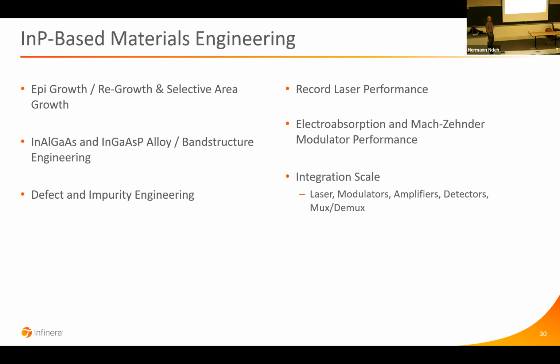We started Infinera in 2001, and some of the things that we did were beyond what is known in the literature: new techniques around growth and regrowth, as well as selective area growth. Also, there are things that people don't appreciate about the band structure, believe it or not, even on a mature technology like indium aluminum gallium arsenide. And probably most importantly, a lot about defect and impurity engineering. With this, we were able to have record laser performance, the narrowest line width indium phosphide based lasers, and the highest performance modulators. And with this, we're able to scale the integration to make some of the most sophisticated photonic ICs that have been developed for communications.